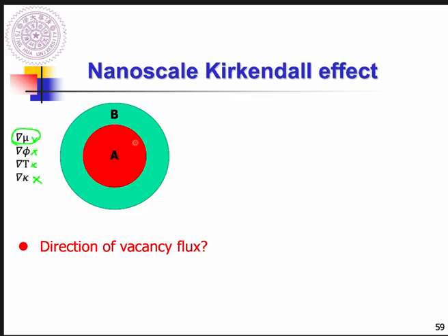At this moment, you can imagine that interdiffusion will happen, right? Because A tends to move to somewhere with lower chemical potential. That will induce the flux. If in your material design J_A is larger than J_B, then in order to reach a net flux equal to 0 at any specific plane inside the material, a vacancy flux will move inward.